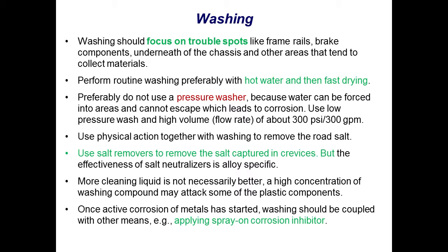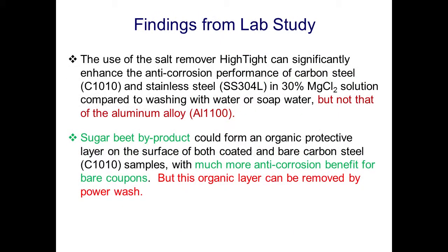Sometimes once you wash it clean and put on a protective coating, or sometimes you don't have a protective coating, you can spray products called corrosion inhibitors. Basically what they do is form an oily layer in most cases to prevent oxygen from accessing your metal. On Monday, the study I presented showed that salt removers are metal specific. They work for certain metals but don't work for other metals. So it's a little risky. And once you do pressure washing, you could wash away this protective organic layer.